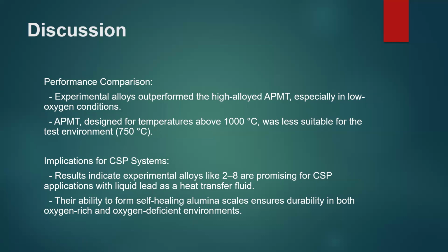APMT, designed for temperatures above 1000 degrees Celsius, was less suitable for the test environment at 750 degrees Celsius. For implications for CSP systems, results indicate the experimental alloys are very promising for CSP applications using liquid lead as heat transfer fluid.